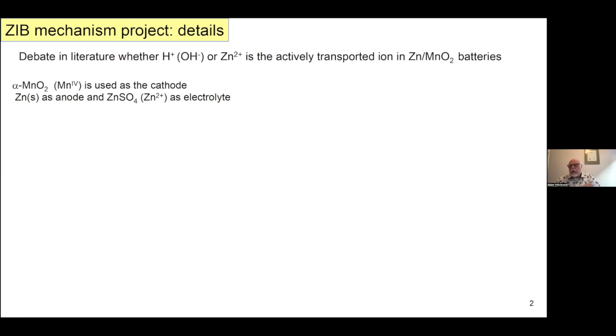That is, it intercalates, it enters inside the structure of a host transition metal oxide, in this case manganese dioxide. And in so doing, it changes the oxidation state. So in lithium iron phosphate, for example, which STXM has been used to study quite a bit, the iron phosphate goes from an iron 2 phosphate to an iron 3 phosphate as the lithium ion goes in. So the lithium ion does not change its oxidation state, except on the anode, but in the cathode of a lithium battery, it's all about oxidation state changes in the host transition metal oxide.